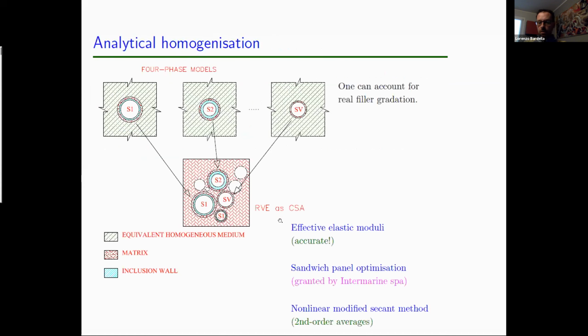About analytical homogenization, we started by developing linear elastic homogenization procedures to have accurate estimates of the effective elastic moduli. Then we got a grant from Intermarine, which is a big Italian company, a big shipyard company in Italy. And so we developed an analytical procedure to optimize the mechanical response of sandwich panels, of glass epoxy sandwich panels whose core is in syntactic foam. And finally, we extended the linear elastic homogenization procedure to the nonlinear range in a so-called modified secant method.